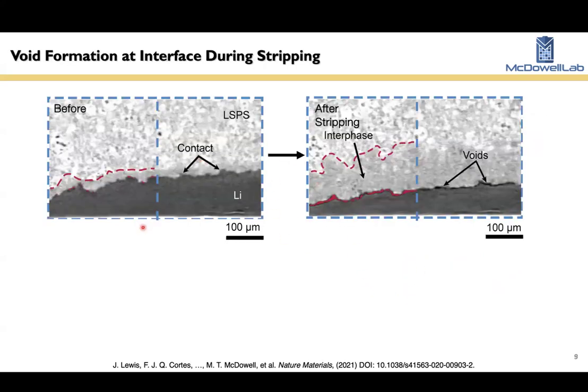Now this is just a 2D cross-section, a reconstruction of the interface. Here we're looking at lithium in contact with a solid electrolyte. This solid electrolyte is a sulfide material. It's lithium tin phosphorus sulfide, one that is not stable in contact with lithium, actually. And so we'll see that in a second. But this is a portion of the interface before any sort of electrochemistry, just the pristine interface. You can see there's fairly good contact.